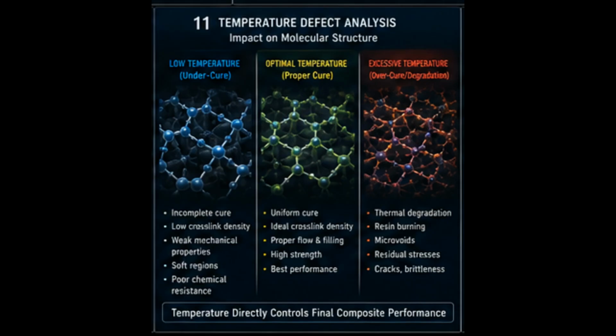Low temperature leads to incomplete cure, weak properties, and poor chemical resistance. Optimal temperature results in high strength and the best performance. Excessive temperature causes thermal degradation, burning, and defects like cracks.